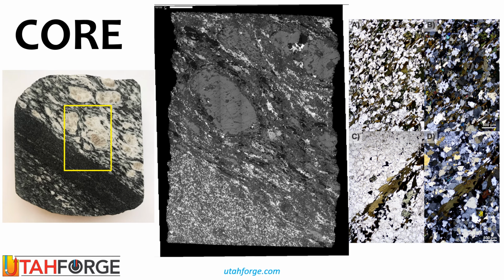This is an example of a metamorphic lithology, an orthogneiss, or plastically deformed granitoid with a modified rock fabric. This sample comes from about 8,500 feet below the surface in 78B32. On the right is a core piece that has been cut in half and polished. From within this yellow box, a large thin section was made with a black and white backscatter image of the thin section at center. This is a 5 millimeter scale.